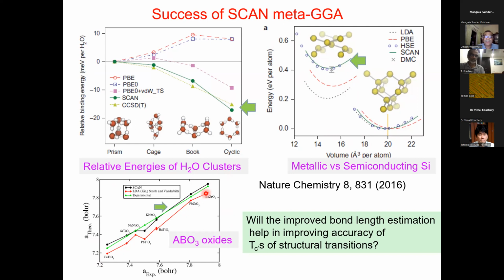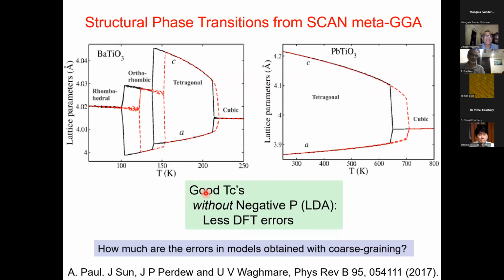So we were of course curious if we can use this new functional in study of ferroelectric phase transitions. And indeed, what we get is you get reasonably good TCs even without using negative pressure, as was necessary in LDA. But the errors remain. The TCs are still underestimated by about 10%. Okay, so some DFT errors are still prevailing.